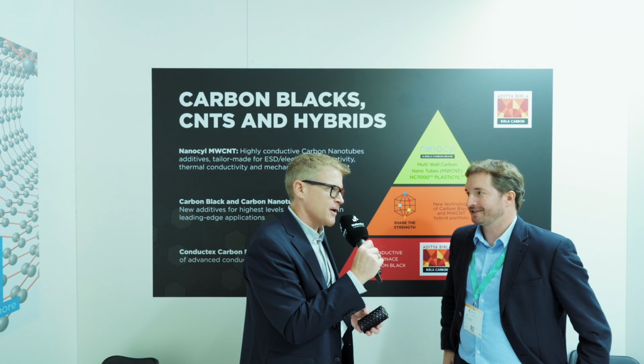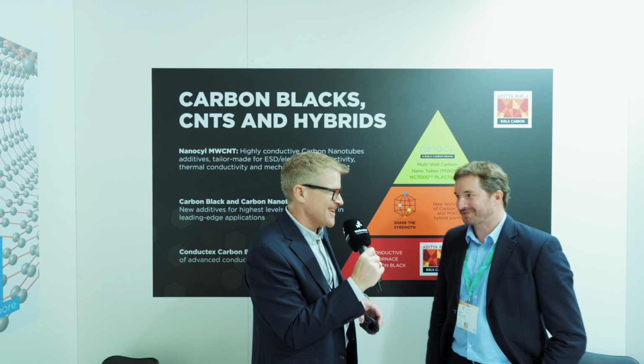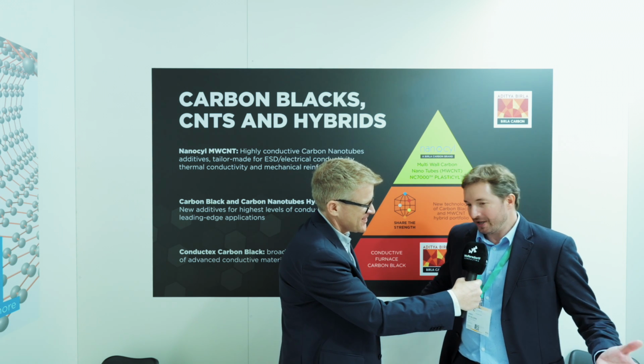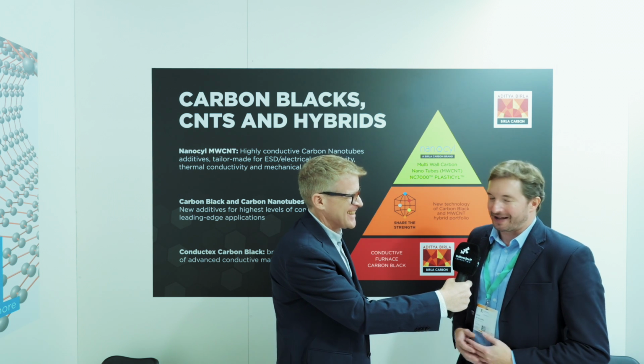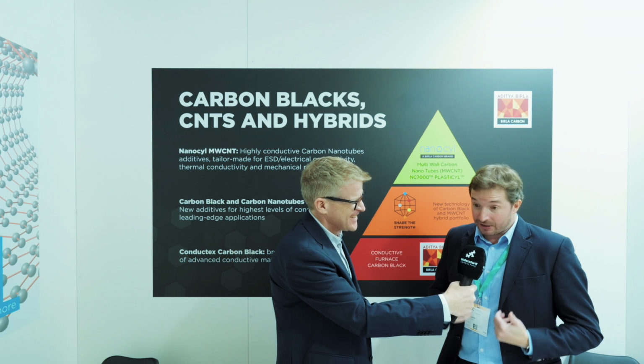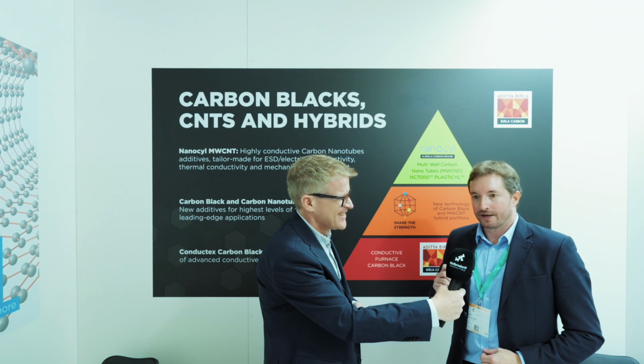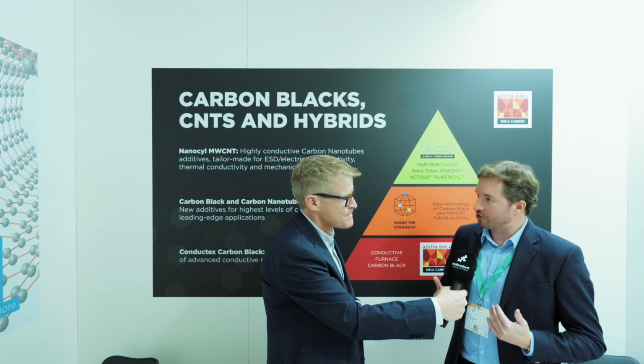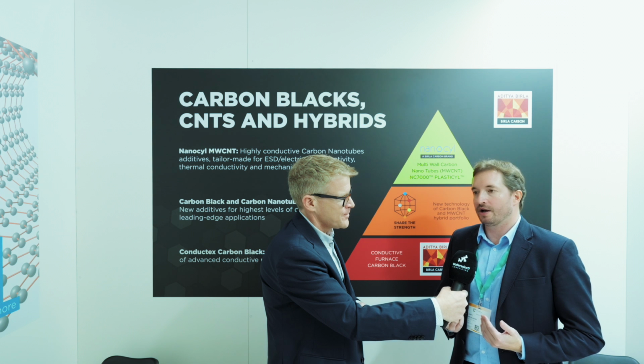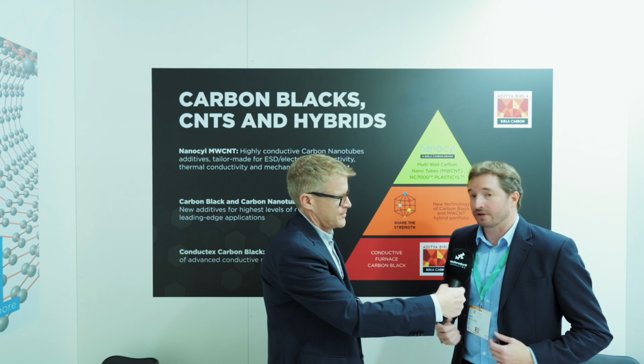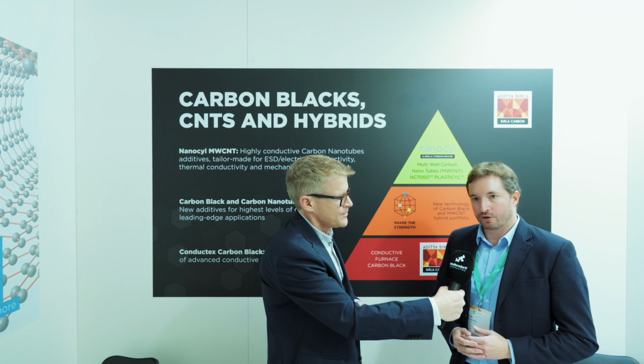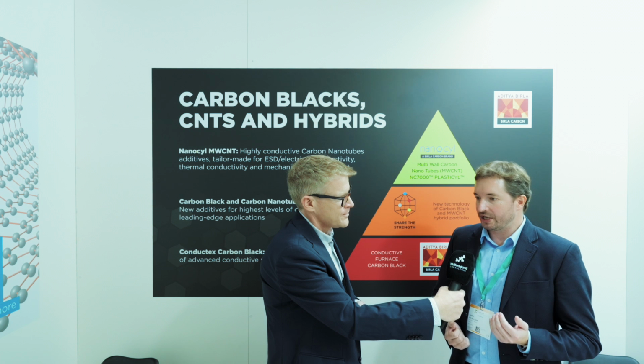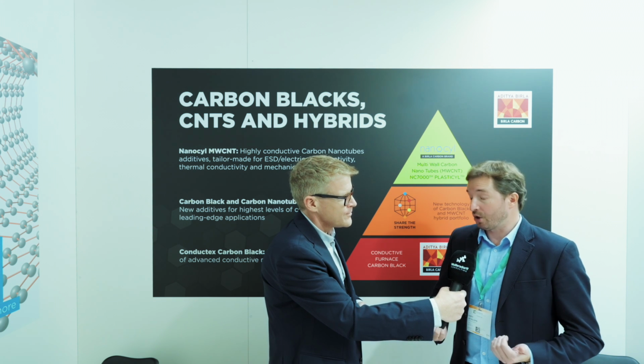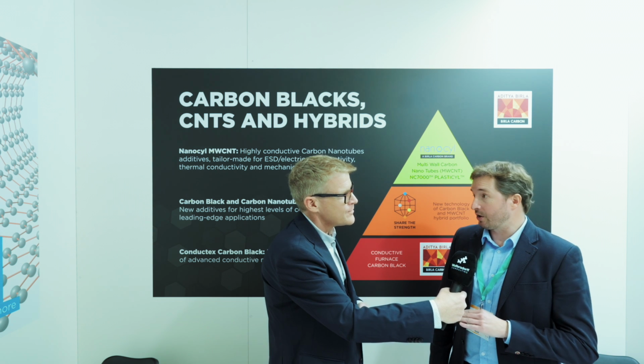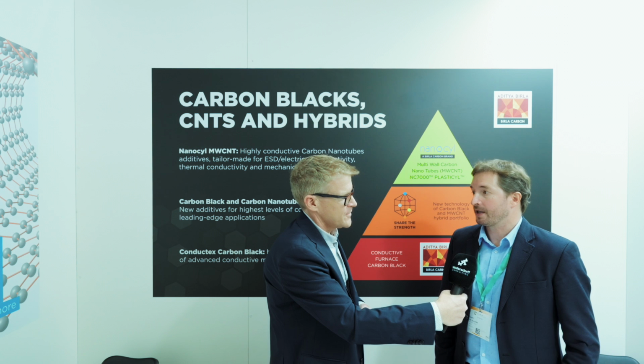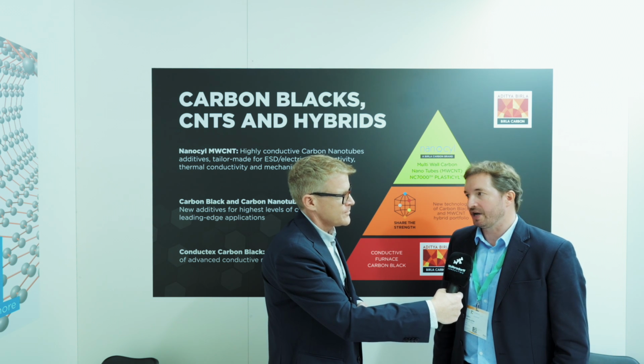But you're still black in color, right? Or do you add so little that it's not black anymore? Yes, well, carbon-based materials are black. Black is beautiful, isn't it? But still, a further aspect here is that the loading is much lower. There are cases where we can reduce the darkness of the material, but we would be talking about applications where the loading of carbon nanotube can really stay on the low side, and typically where you would have a very small thickness of the material. When you add up the layers, obviously you're getting more darkening effects.